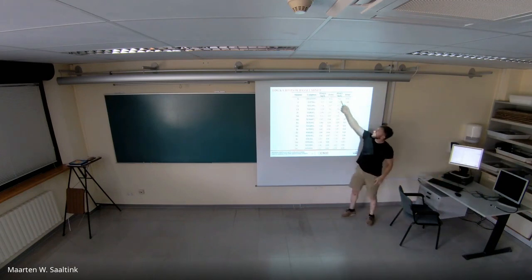Regarding basaluminite, it is a more difficult mineral, but we see that the values are around 1. So bidentate reactions are not occurring at the surface of this mineral. And if we compare the values, they are more or less in the same order of magnitude.